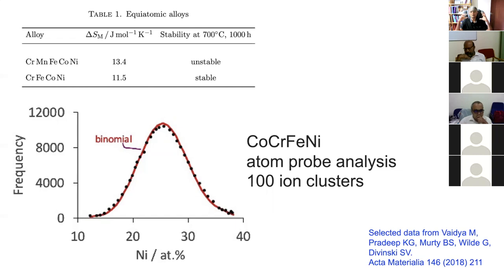Now, when you do this analysis using the atom probe, of course, it refers to a particular condition in which you produce the alloy. You produced it and you've allowed it to cool to room temperature. And as you'll see later, if you just examine it after production, then you may have cooled rapidly enough to stop anything from happening. So ideally, what we should also do is produce the same results by annealing at a variety of temperatures and again looking at this distribution of atoms.